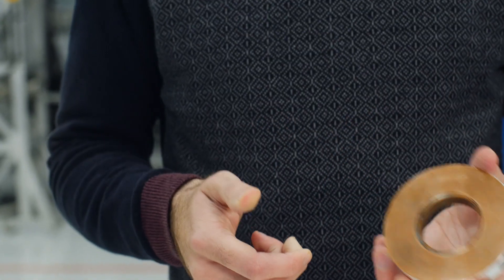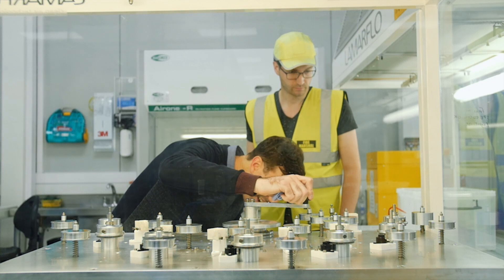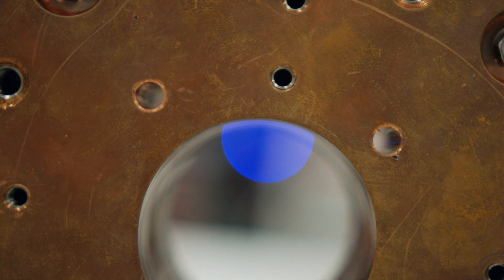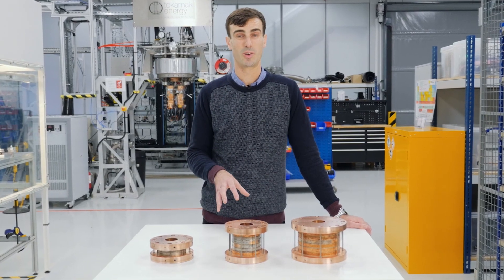Not only are these coils resilient against quench, but they're also extremely defect tolerant. Magnet engineers often worry about defects that occur in these tapes naturally — small cracks caused during the manufacturing process. We really wanted to test whether these things were important for the design of a large scale HTS magnet. To our surprise, we found that these coils are able to withstand substantial degrees of defects and not only be tolerant, but completely stable as an end result. What we've actually done is taken one of these coils and drilled physical holes through the windings and then retested the coil. These don't exhibit any particularly aggressive signs of instability — they just generate less field than before because they've lost a few turns. That's really because the design of the coils allows the current to share around defects in a way that makes them extremely defect tolerant, which is crucial when you want to make large scale superconducting magnets.